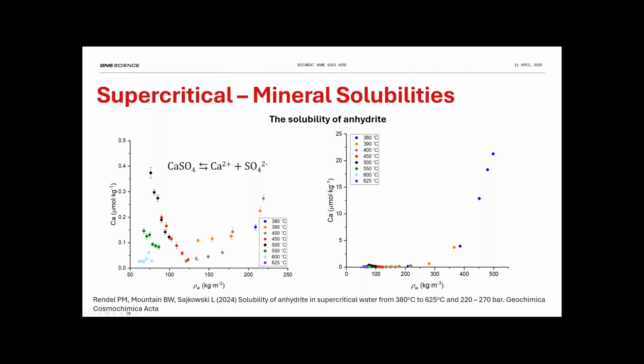It's counterintuitive because we can see as the density of the water goes up here, the solubility goes up. But if we look in detail at the lower end of the data, you can see that as the density of water is decreasing, the solubility is actually increasing. And this is probably because we're now forming a volatile calcium sulfate phase. It's not actually an ion anymore. It's actually calcium sulfate gas at these very low pressures.